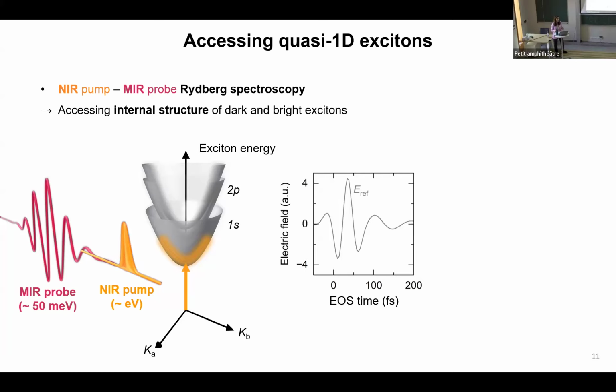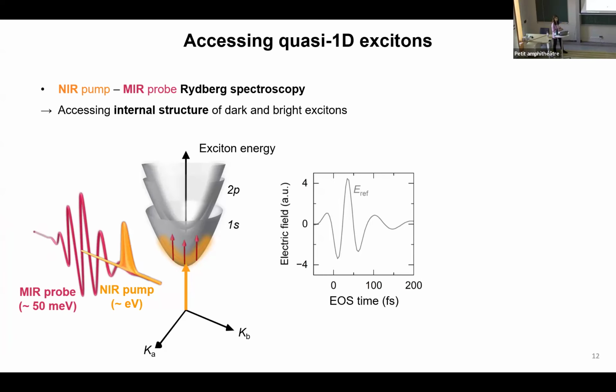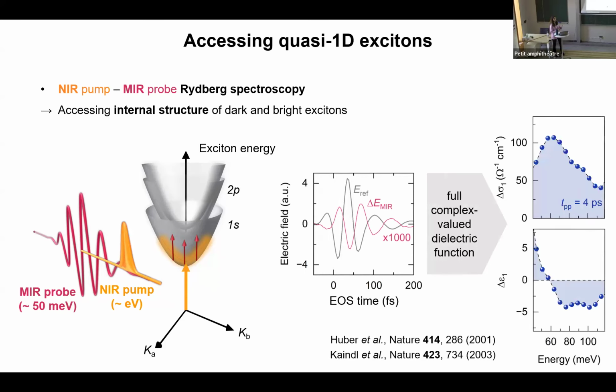So our trick is to now make our mid-infrared radiation work. We come with our mid-infrared radiation at a certain delay after the near-infrared pump, and we trace again the changes in the transmitted mid-infrared electric field of light, as I show in an example here. Because with our oscilloscope we are simultaneously recording the amplitude and the phase of this mid-infrared radiation, we can retrieve the full complex-valued dielectric function of the material. And in this pump-induced dielectric function, we retrieve information about the excitons.